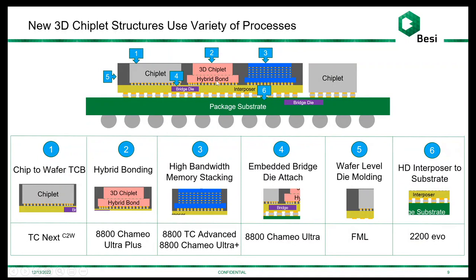Hybrid bonding is the most advanced interconnect that allows very fine pitch direct interconnection between the back end of line buildup layers on a silicon device to a similar back end of line or TSV structure on another device, allowing you to make very low impedance contacts and very high density, high bandwidth contacts between chips. And this really allows designers to design in 3 dimensions without implementing energy sucking IO buffers and things like that between the chips. It's really a direct connection. So this is the most advanced interconnect that you might find in some of these chiplet systems.